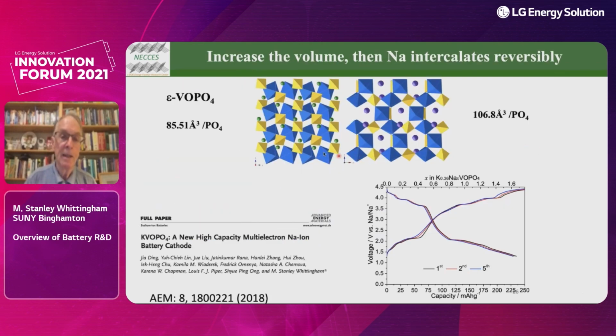So this is our epsilon phase. This is the potassium phase. And here is our material. We charge it up first, take out most of the potassium, okay? Then we can discharge it reversibly, but what we're left with is about 1/3 potassium in that lattice. We're still trying to get that last potassium out, but the sodium will go in and out. The voltage changes a bit too much, more than we would like. And folks in Japan, Komaba's group, I think, have studied potassium intercalating in and out of this structure as well.